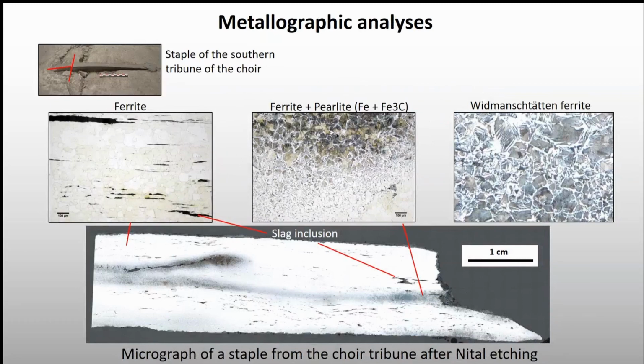the different artifacts that were sampled. So here you can see the staple of the choir tribune that we spoke about earlier. It's the same here. You have how the weight was cut, and the surface is polished and etched with nital etching, which helps reveal the steely parts, the carburized zone of the iron. So here you can see we have a heterogeneous ferrous alloy with many ferritic zones here, the bright ones, and some more steely parts here, the darker ones.